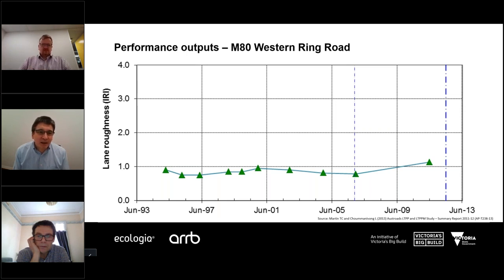Now, if you know about roughness and ride quality on new pavements, if you get less than 1 IRI, meters per kilometre, you're doing pretty well. And you can see here at the start, this pavement was built to a high standard with a very smooth ride quality, less than 1. However, you look across the 10 years and the whole design life, and it stays pretty constant.